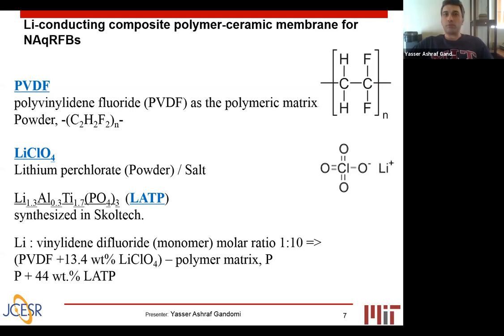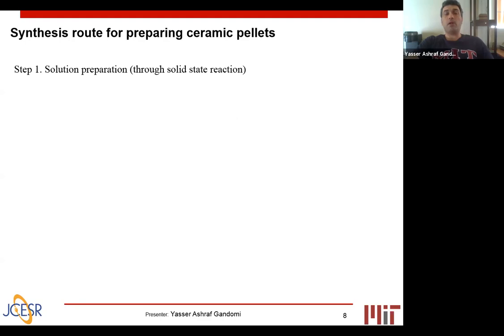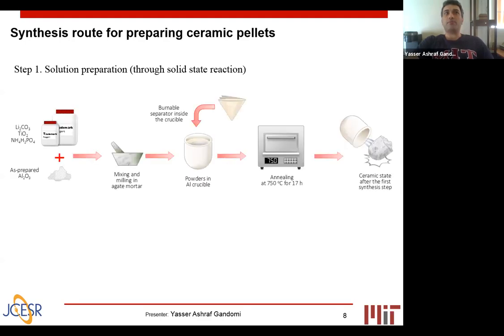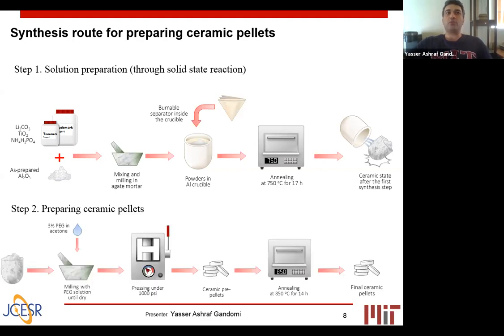13.4% for the salt, and 44% for the ceramic is what we have used for synthesizing the composite ceramic structures. To prepare the ceramic pellets, we used lithium carbonate, titanium oxide, ammonium dihydrogen phosphate, along with aluminum oxide. After mixing and milling, adding a burnable separator, and undergoing the first annealing step at 750, we prepared the ceramic powder material. Then we took that ceramic powder and added 3% PEG and acetone. And after compressing and a second annealing step at 850, we could prepare the final ceramic pellets.